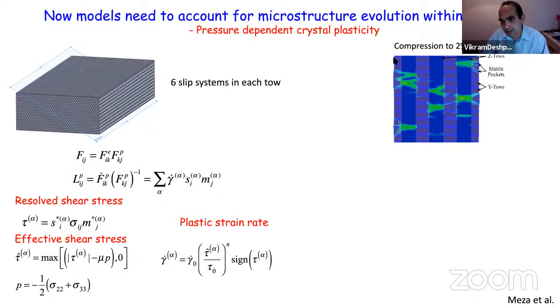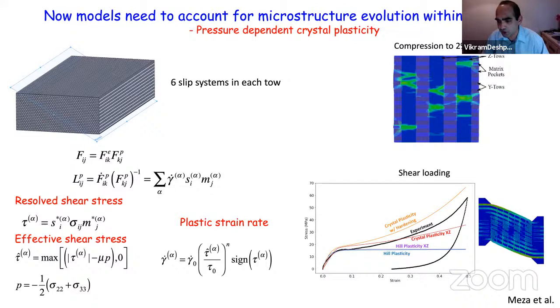And if you use that, and this is Lucas Meza's work, when you do this compression test you can see that you start predicting these kinds of kink reflections, etc. And all the tows are discretely modeled. Similarly, if you start modeling those shear experiments, the black line is the experiment. The orange line is the crystal plasticity model with the pressure sensitivity. If you don't include the pressure sensitivity of the shear strength in the tow, then you start under-predicting the experiment.